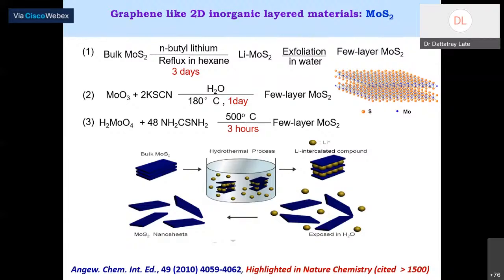So what we need is bulk MoS2 and n-butyllithium. You know, n-butyllithium is very strong, so we need a very careful experiment. We have to put the bulk MoS2 powder in n-butyllithium and take it into hexane, and reflux in hexane for 3 days. What happens now is that lithium loves this layered MoS2.